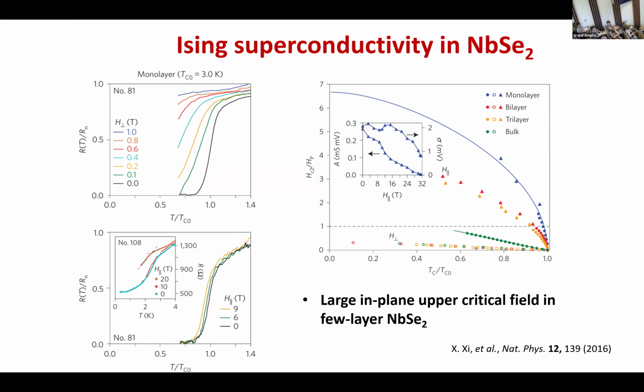Second comment is that with Ising spin-orbit coupling alone, theoretically, the Pauli limit could be exceeded by an infinite amount. Oh, yes. So the fact that it's finite is due to some Rashba, which is much smaller than the Ising. Okay. Yes. There could be some Rashba. Yeah, I mean, we had a recent PRB paper, and it's not due to Rashba. Okay. They neglect the gamma band, and the gamma band does expect a finite.